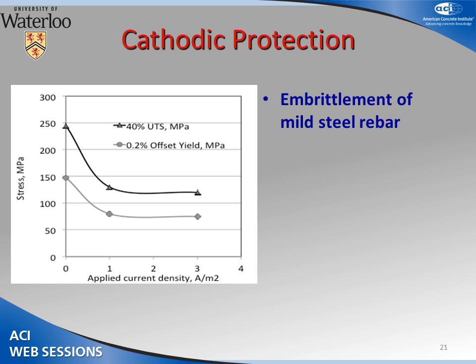And you can see that this is the applied current density. I think it was applied for 2 weeks. And you can see that he was applying to 40% of the UTS, ultimate tensile strength. This dropped from about 250 down to about 125. In other words, it was 50% less. Similarly with the yield stress. So this was the first time that people had actually discovered that ordinary, everyday rebar can in fact be susceptible to embrittlement.